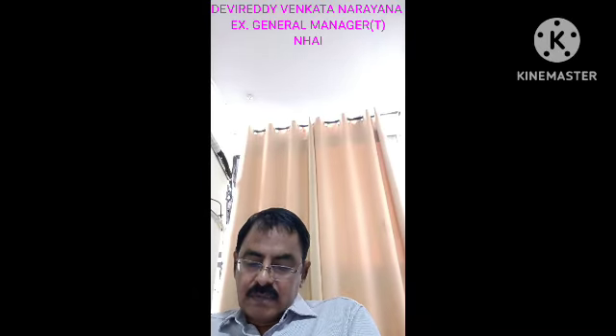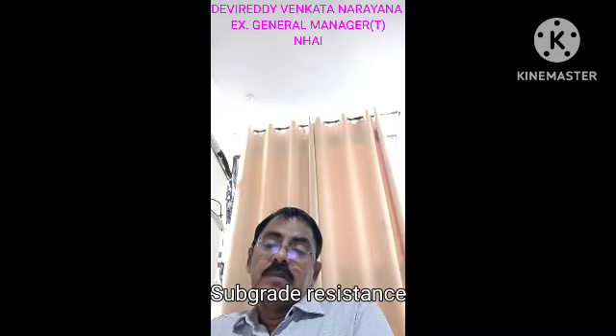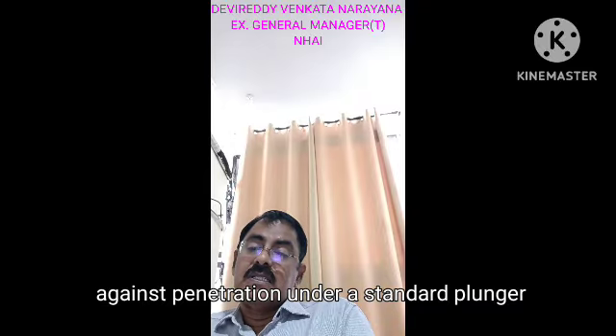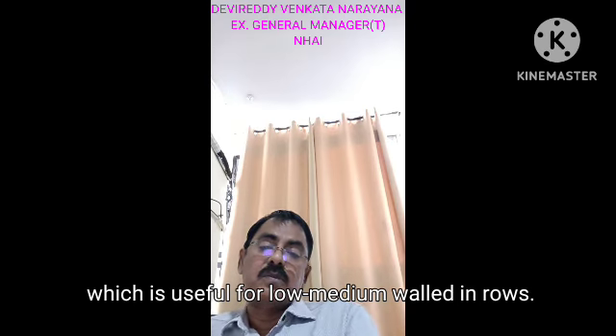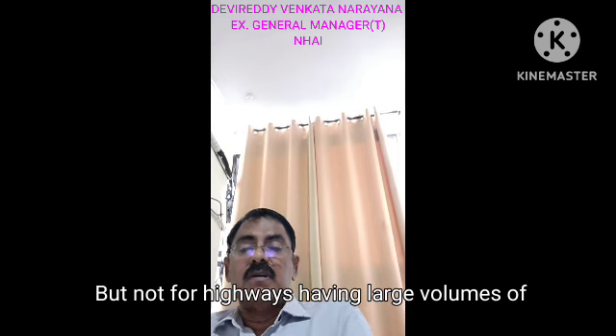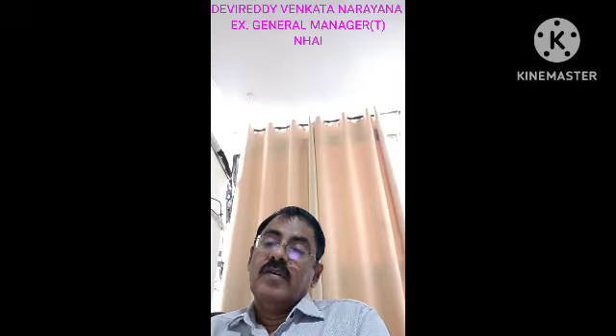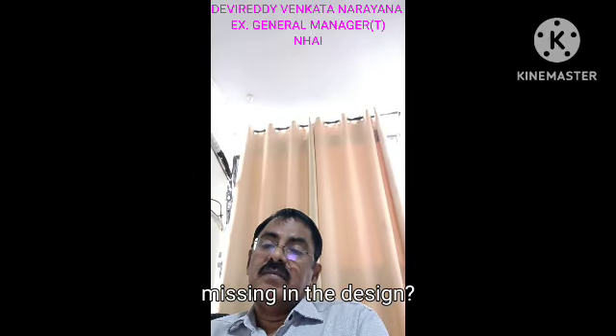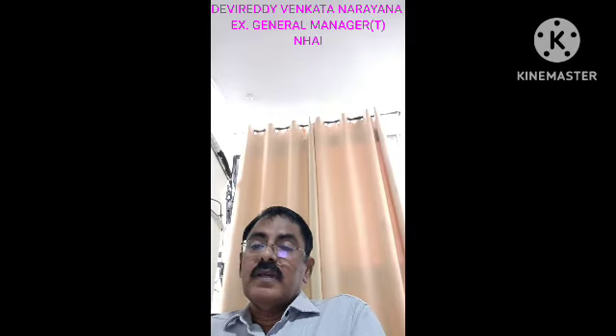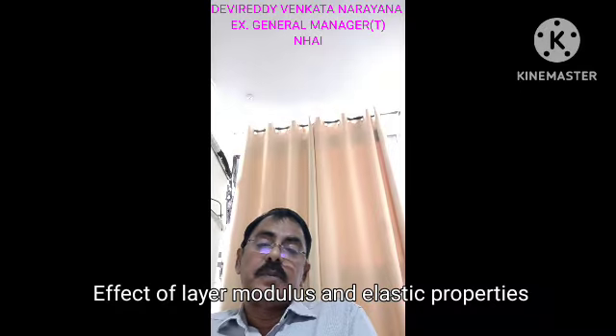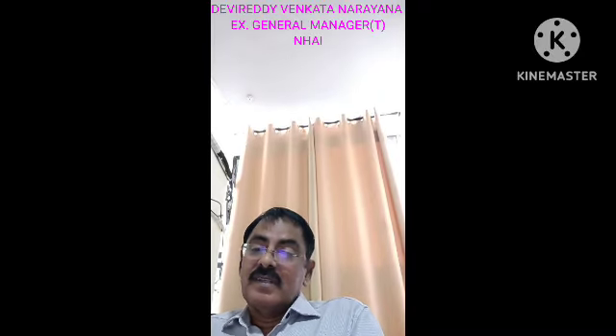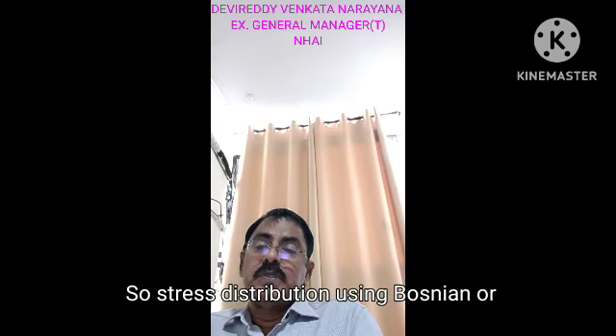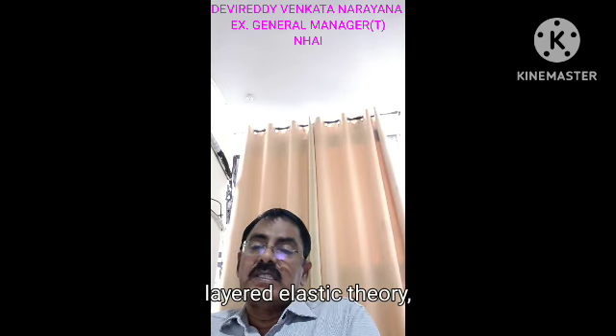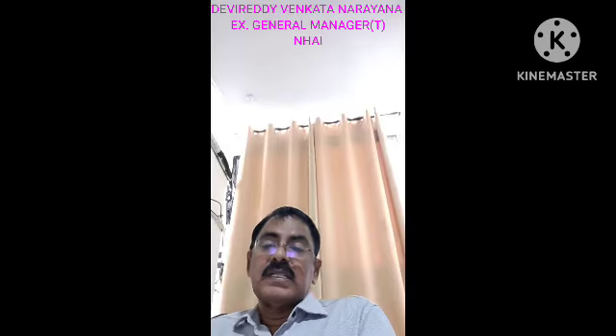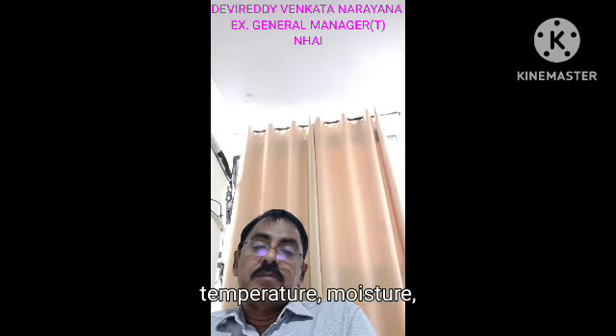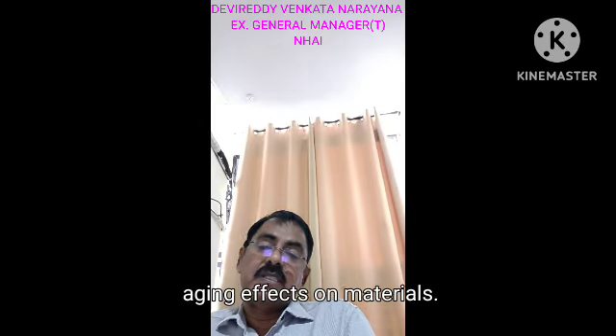So what it reflects is subgrade resistance against penetration under a standard plunger, which is useful for low and medium volume roads, but not for highways having large volumes of traffic. What is missing in the design? The effect of layer modulus and elastic properties of bituminous base layers is missing. So stress distribution using Boussinesq or layered elastic theory, cumulative fatigue and rutting under repeated loads, temperature, moisture, aging effects on materials.